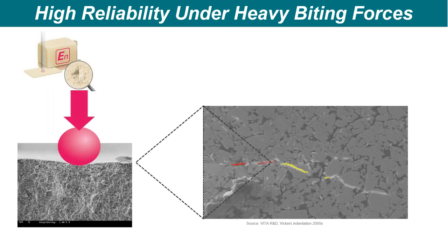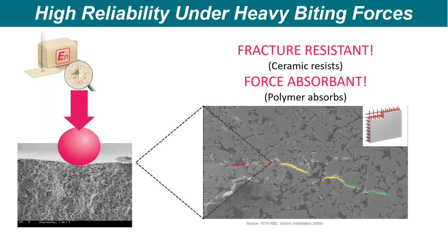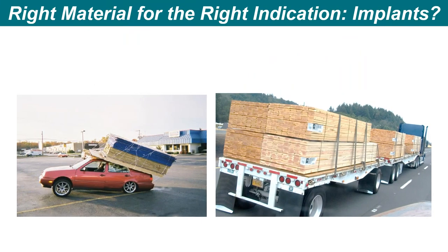One of the primary reasons why it's such a high fracture load is because when this enamic is loaded by the patient, if it goes into a severe parafunction, or the loads are such that the patient is chewing a bone or a glass or whatever it is, this material, as opposed to fracturing, will actually bend. It will distort. It will deform before it fractures. That ceramic will resist the fracture. The polymer actually absorbs the loads, the energy created by that heavy biting patient, and that energy just dissipates. So we want to have the material that works the best for the situation, right?